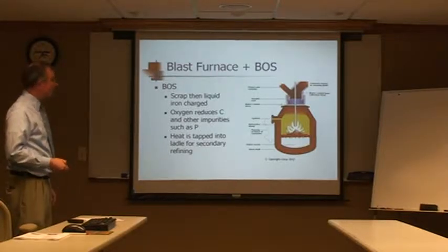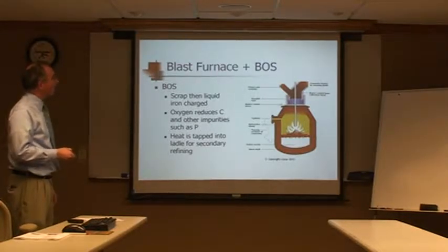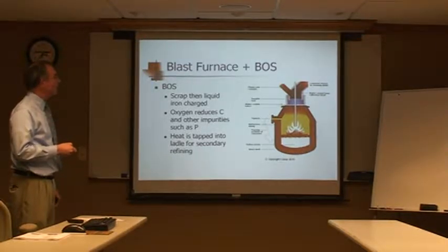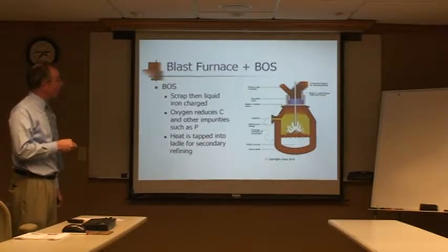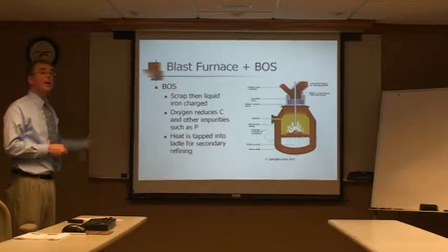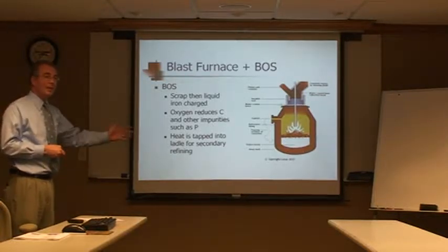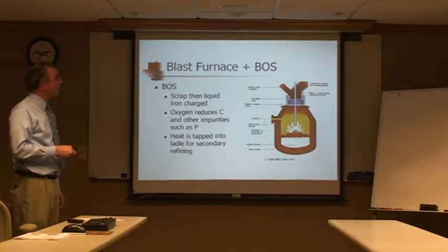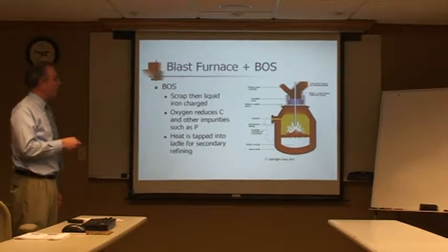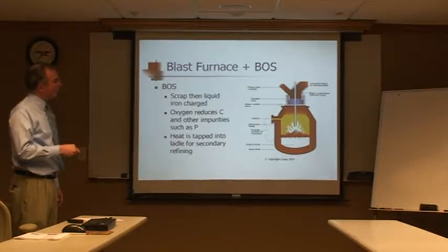So here is our vessel for basic oxygen steelmaking. What happens is, if you see this shadow right here, this furnace will tilt, and then in addition to the liquid iron that we had, we'll also use scrap in this process as well. So we put scrap down here on the bottom, and then the hot liquid is poured into here, and this oxygen lance comes down.